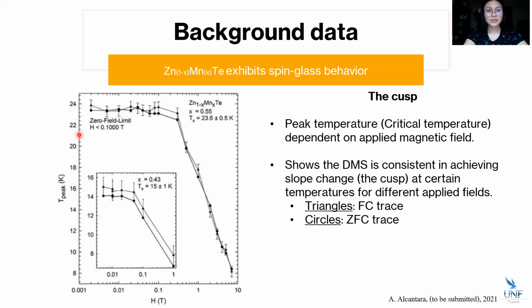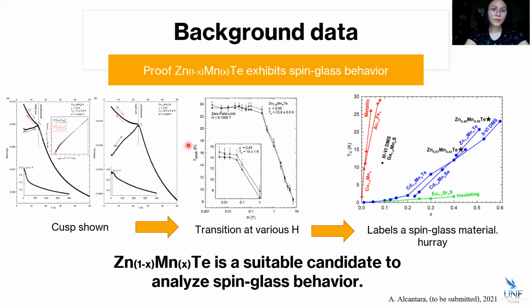So this is a plot of the transition temperatures as a function of applied field. And you can see here that the triangles of the field cooled and the circles of the zero field cooled trace. You can see that it does transition at different levels of applied field, and then right around 1 Tesla, it drops significantly. And this is due to the energy of the applied field now affecting the exchange interactions. And so to sum up the experimental data to prove that zinc manganese telluride is a spin glass material to study, we show that there's a cusp that occurs in both field cooled and zero field cooled. We show that the spin glass transition happens at various levels of applied field. And so we can go ahead and add this to that evolving plot where you can see our points here now as stars. So we can go ahead and say that zinc manganese telluride is a suitable candidate in analyzing the spin glass behavior through its electronic properties.